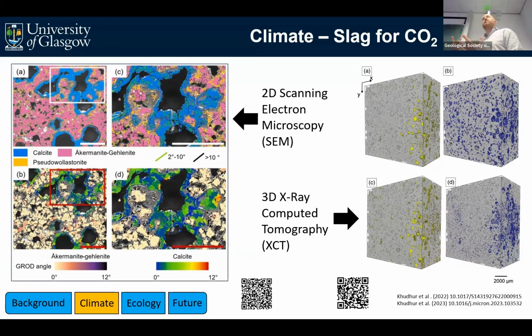So that's a 2D approach that we've used to try and understand this process. We can also do it in 3 dimensions using a CT scanner or micro CT scanner, really just the same as the one you would get a scan in at hospital, just a bit smaller, designed for looking at rocks and related things. And these 3D block models on the right essentially just show that we can use this technique to look inside these pieces of slag and understand, where is the CO2 going? Where is it being mineralized? And we can also use the software associated with this micro-CT to do clever analysis to quantify how much CO2 you have mineralized within a certain size or volume of piece of slag.